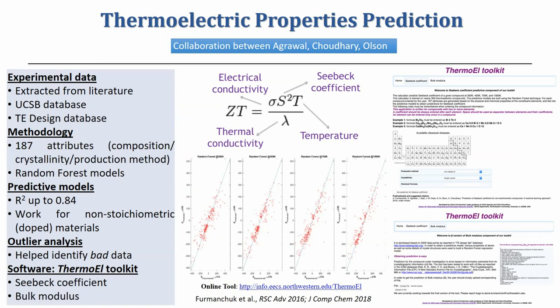Here we are using experimental data from the UCSB database that Taylor had developed, and also the TE Design database for another property. For any of you who know anything about thermoelectrics, you know what ZT is. It's the figure of merit for thermoelectric materials, and it depends on the Seebeck coefficient, temperature, and electrical and thermal conductivity. As of now, we made models for Seebeck coefficient and bulk modulus, which indirectly goes into this formula. And using composition and production aware attributes, you could get R square up to 0.84.